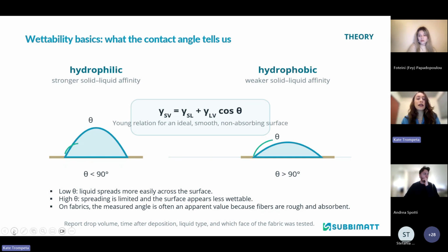All the phenomena are guided by the Young equation. So we separate the materials into hydrophilic or hydrophobic. We could also have super hydrophilic or super hydrophobic cases. For a hydrophilic material, we have stronger solid and liquid affinity. And for a hydrophobic material, we have weaker solid-liquid interactions. The Young equation combines the surface tension of the solid with the liquid, or the solid with the gas, or the liquid with the gas.